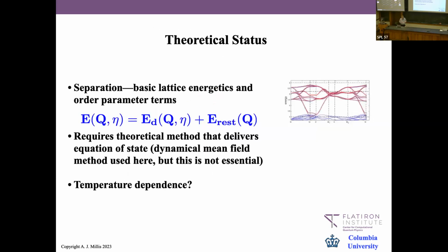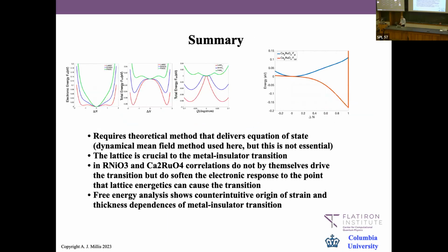So that's what I told you so far. I find this very appealing because there was this long and essentially pointless argument between the many-body electron school of thought and the density functional lattice degrees of freedom school of thought about which one was in charge of the transition. Now we have a reasonably well-defined mechanism for answering that question in each compound, and in the two we looked at in most detail, the answer is both. I should say that to make this work, really what you require is three things: a theoretical method—we use density functional plus dynamical mean field theory, but it's not essential—that delivers an equation of state, and a linear coupling between the electronic order parameter and the lattice degree of freedom.